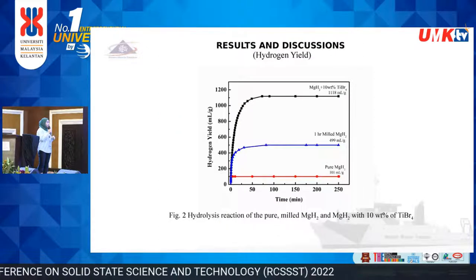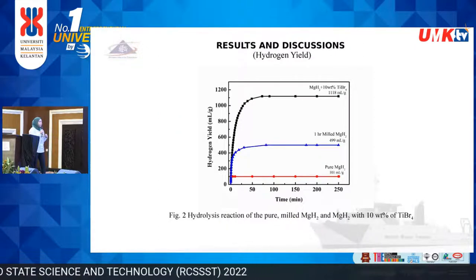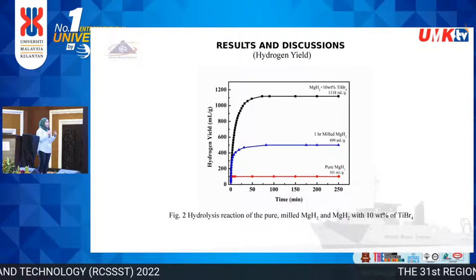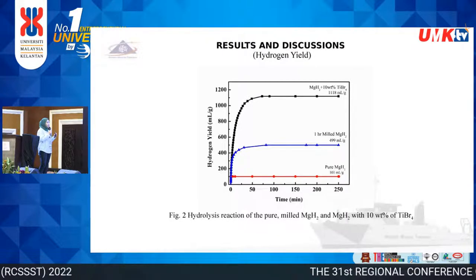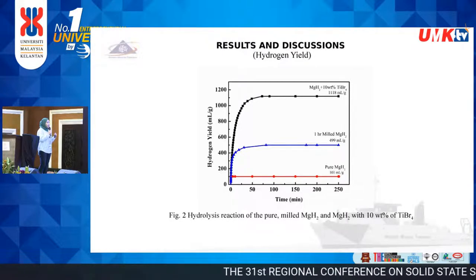This is the result for the hydrogen production. Pure magnesium hydride has the lowest hydrogen production, which is 101 milliliters per gram.